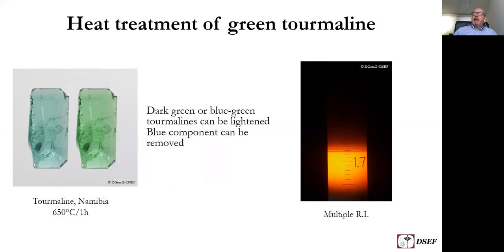Now, already in 1932, it was George Will, the founder of the German Gemological Association, who found out that when you heat treat these bluish tourmalines, you can get rid of the blue, producing a green. And at these times, actually, green was more sought after than blue. And so all of these tourmalines have been treated to remove the blue component. This can be done at temperatures of around 650 degrees centigrade in about 1 hour. So we did this in our own oven here in our laboratory. And is there a possibility to identify that?